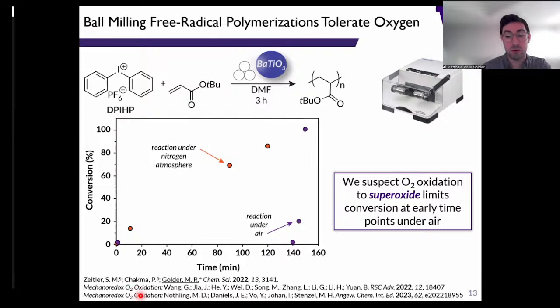What we think is happening, we don't have any experimental evidence from our own experiment here, but some recent work in the literature suggests that O2 oxidation to superoxide may limit some of our conversion at early time points, in that there is some rate associated with scrubbing, in quotes, of the atmosphere of O2, and once all of the O2 is scrubbed from the headspace of our sealed vessel, the radical processes can begin to proceed.